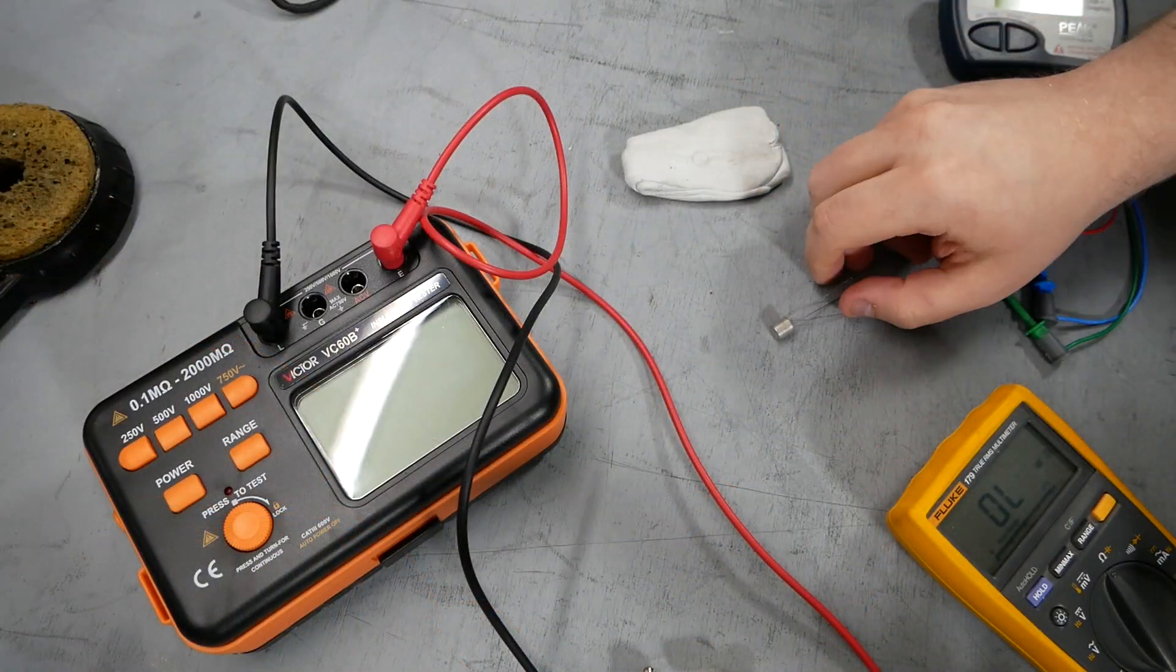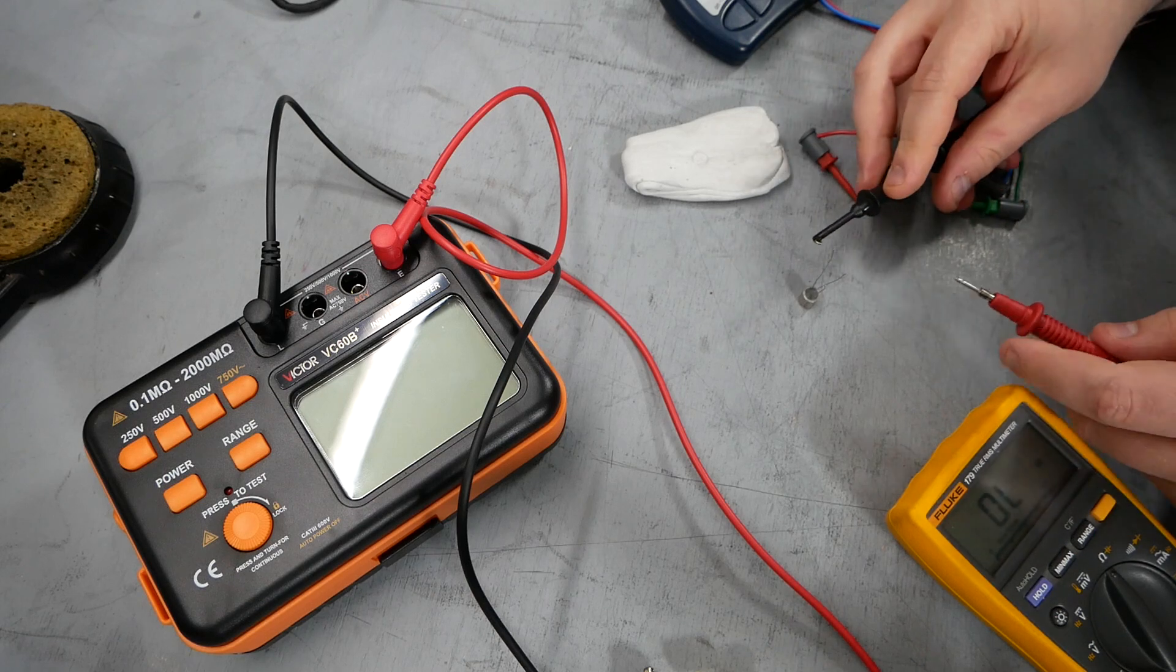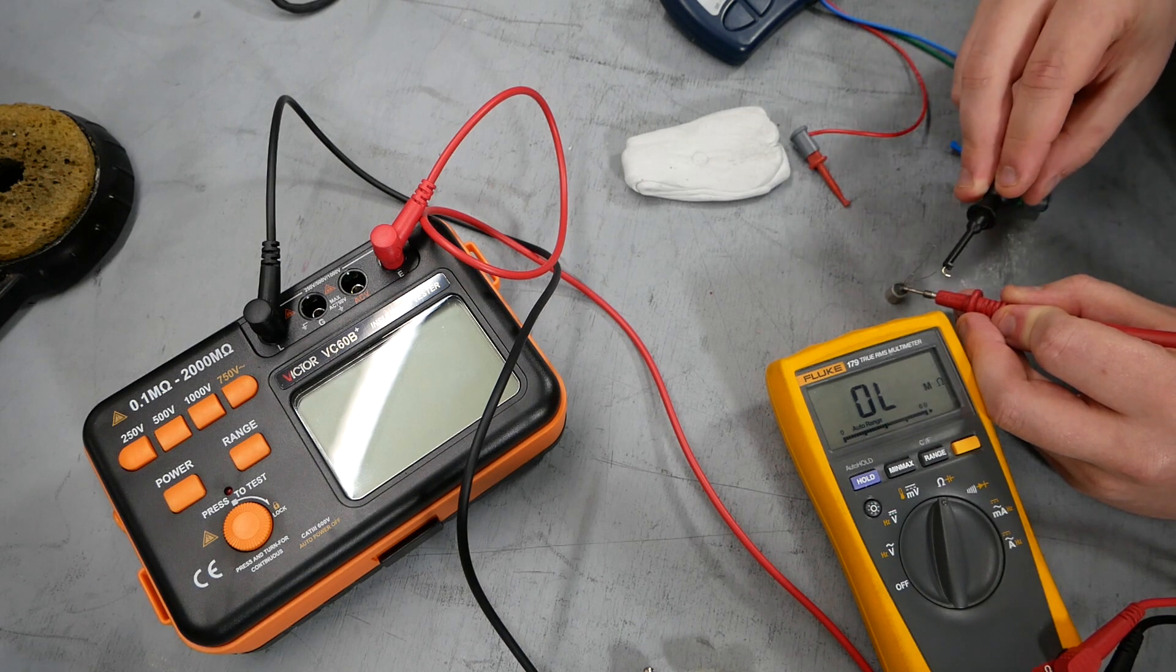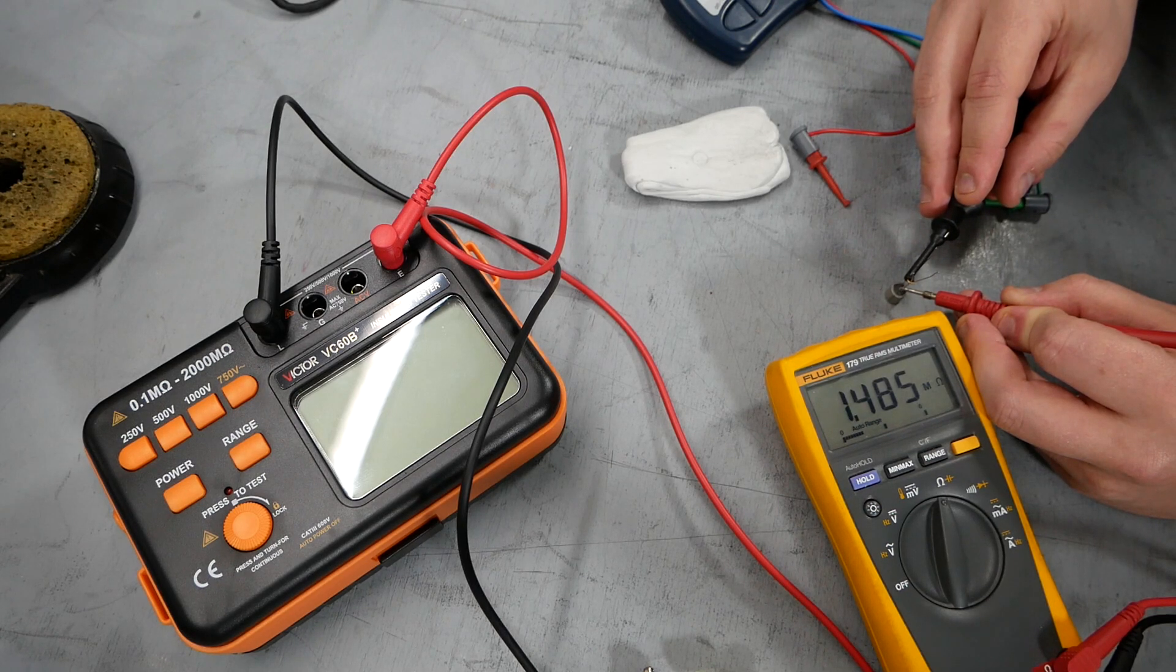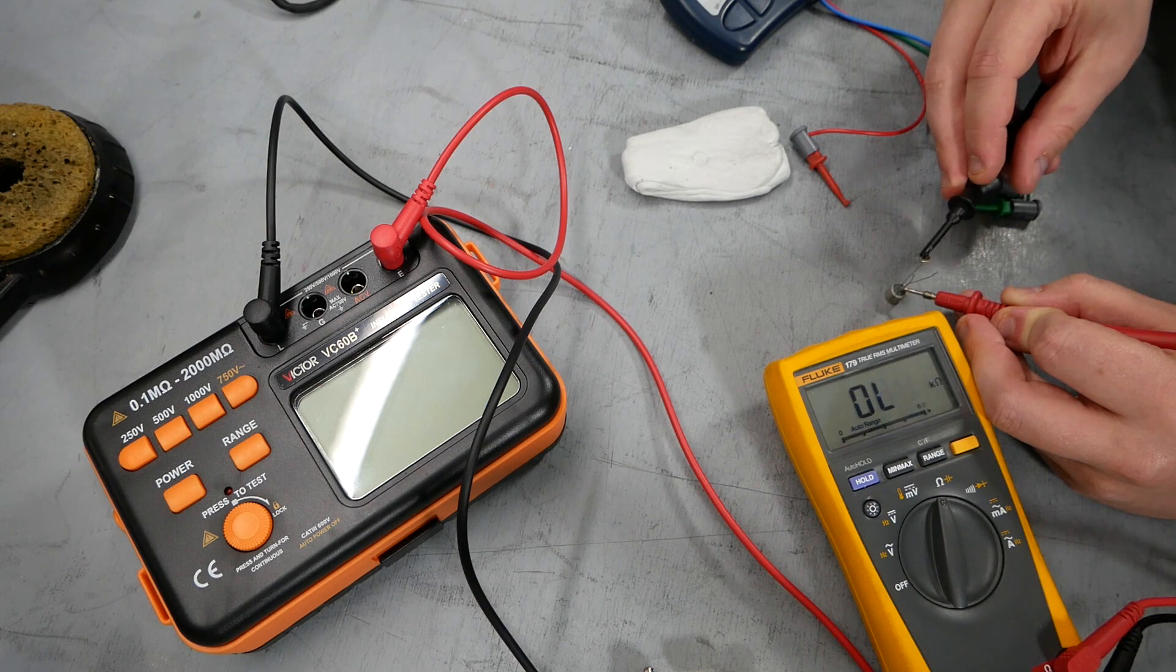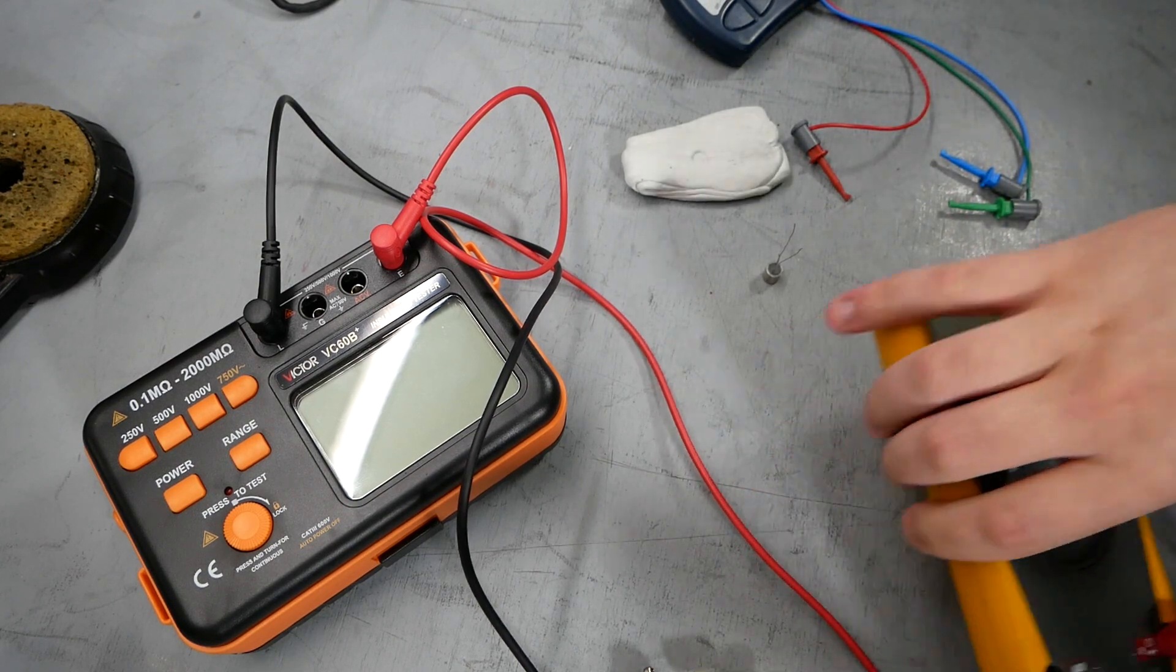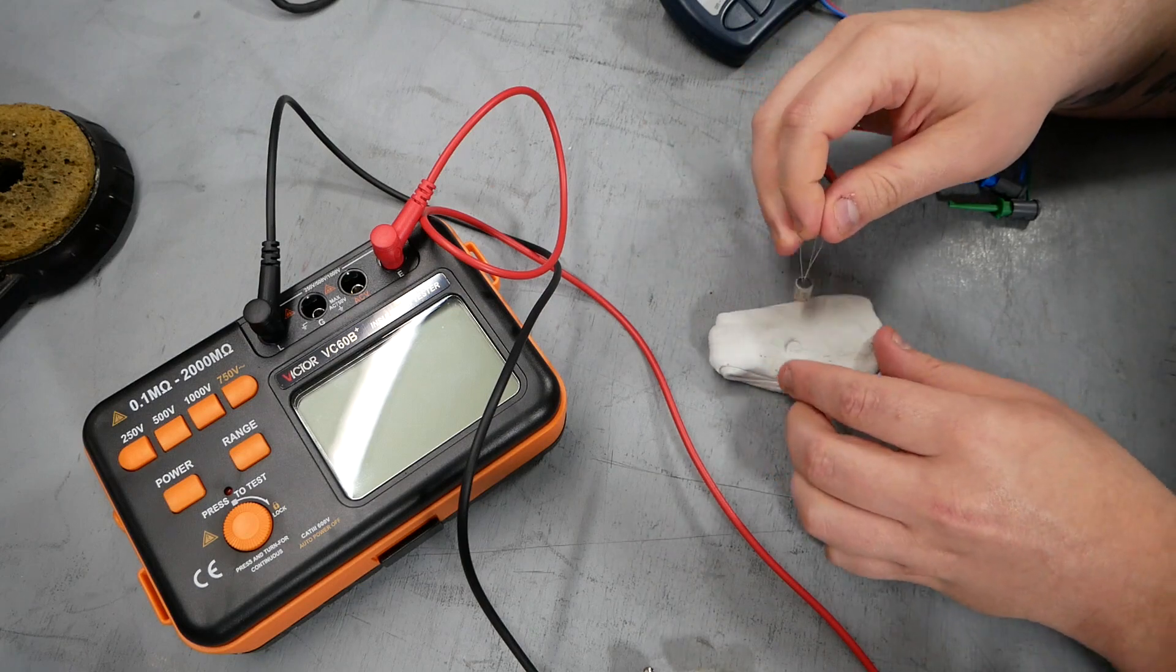Let's try another one. So I've got one of those CV7089 transistors here. Again, this is the one with the cutoff shield lead. So we're gonna have to do a little something to be able to touch that. So I'm clipped onto the emitter here. It's measuring resistance to the shield. 18 ohms, which is probably a whisker. Let's try the base. Base is eight and a half K. The collector. Oh, sorry. This is the emitter. 1.485 meg. This is the collector. 18 ohms. So there appears to be a whisker from the shield to the collector, but there isn't whiskers touching either the other electrodes, but they could be very close.